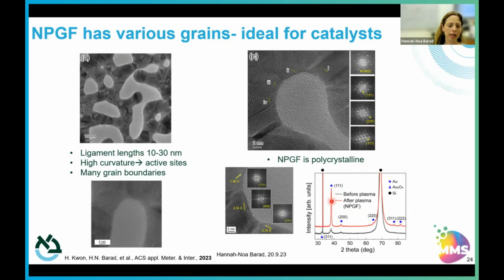And what's interesting is that before our plasma treatment, we actually have some gold oxide on the surface, but after our plasma treatment, when we move from nanoparticles to these nanoporous mesh films, we end up actually having just pure gold. So besides forming this mesh structure, we can also purify further our surfaces. So as a kind of test subject, we went with gold, as you can see over here.